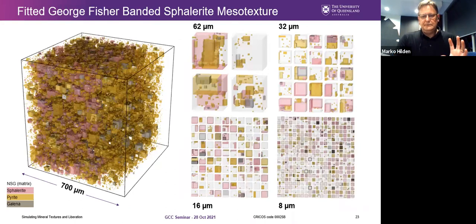So the fitted model of the texture contains a band of gangue mineral on the right and a band of pyrite-rich material as well, which doesn't contain much of the sphalerite, the pink mineral grains. And the texture is extremely fine. So this texture is a representative or archetypal texture that's useful for modeling. It's not like a rock handpicked off the stockpile, which can vary in composition and might not be representative of the ore. Because it's been backfitted from a ground ore, it's representative of that stream.